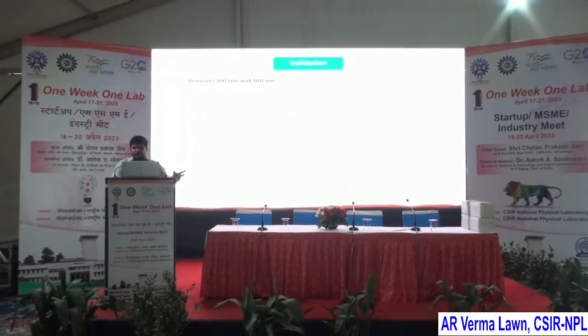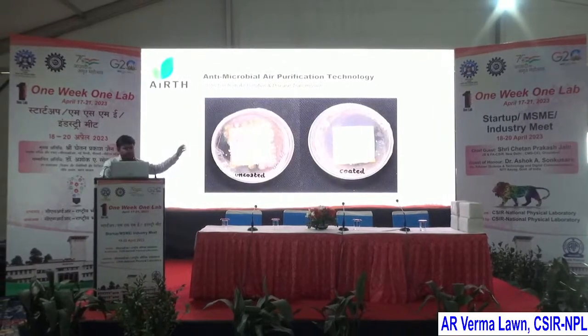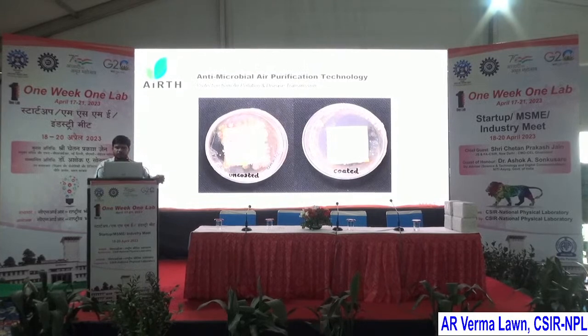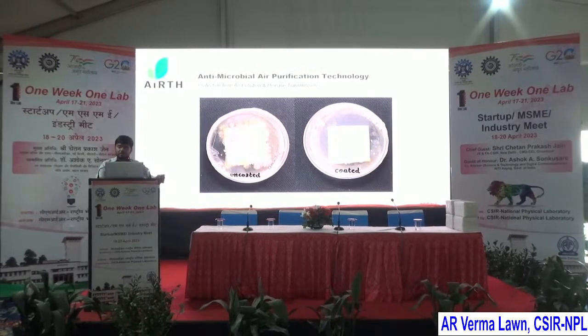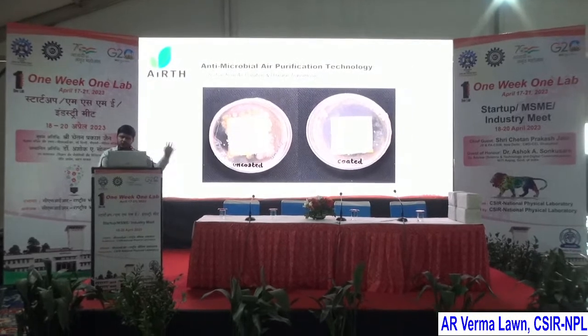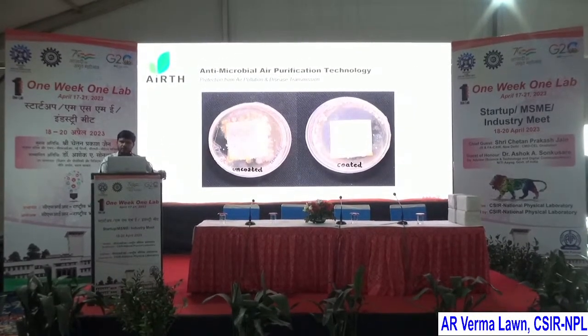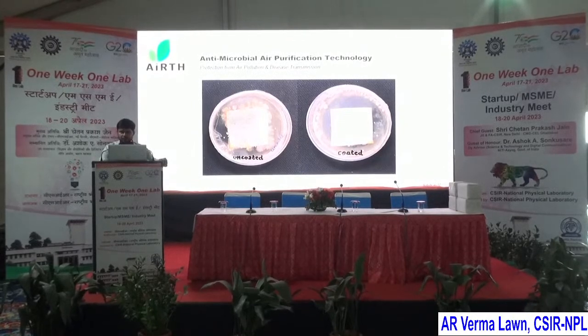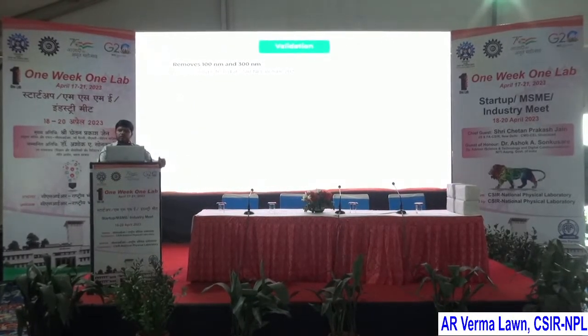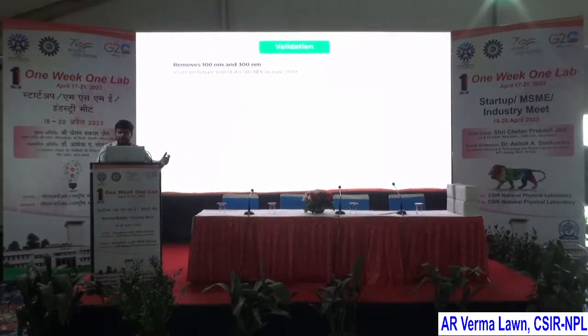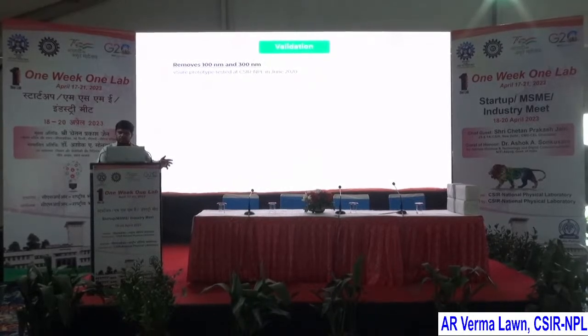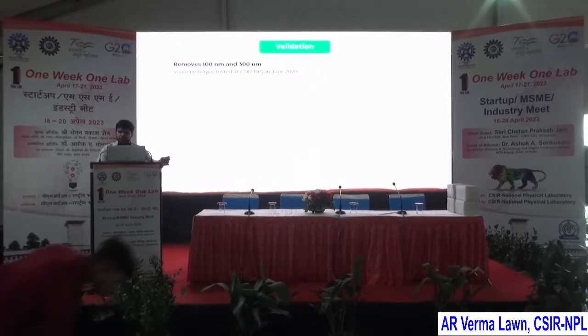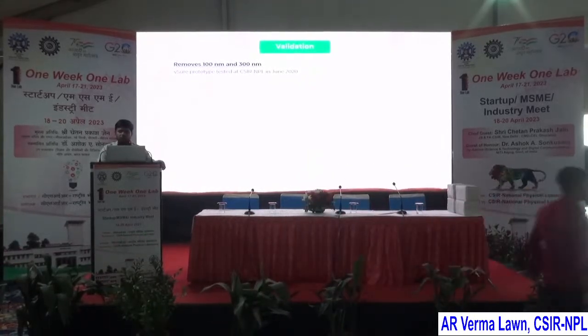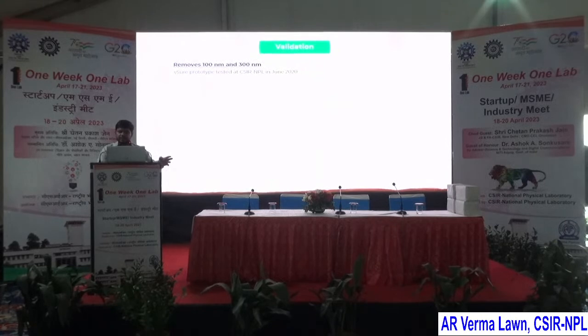So the validation that we have done, what you can see on the second slide, the coated side is our filter that is coated with plant-based enzymes. Polyphenols destroy germs. Not only does it capture it, but also destroys it. That is how we are different from any other kind of filter that is available in the market. The validation that we have done, it is able to remove 100 nanometer, which is approximately the average size of SARS-CoV-2, and 300 nanometers, which is MPPS, the most penetrating particle size which is able to go through a filter media. That has been tested here at CSIR-NPL in June 2020.